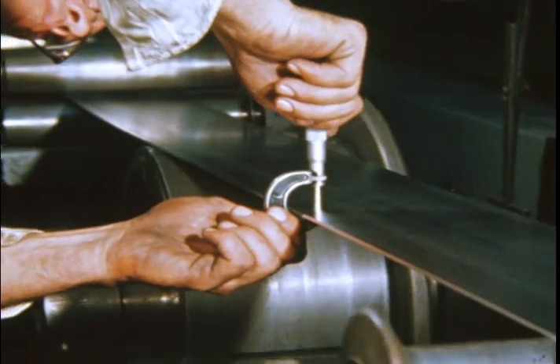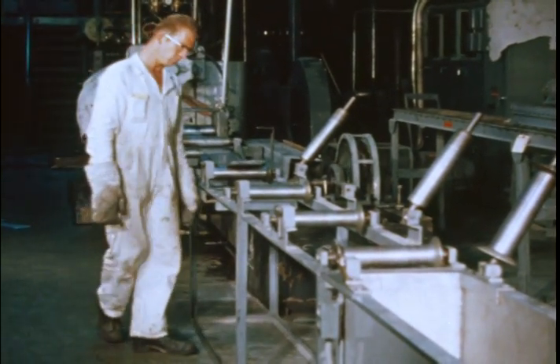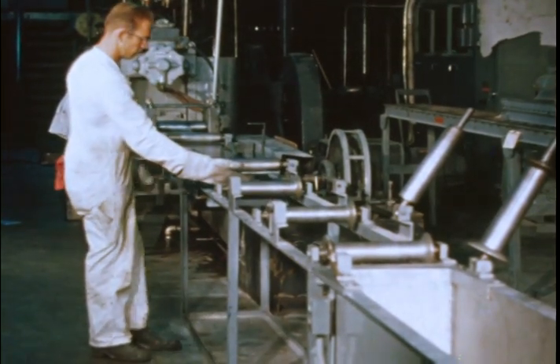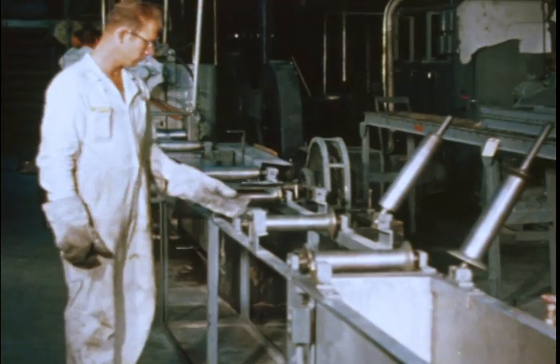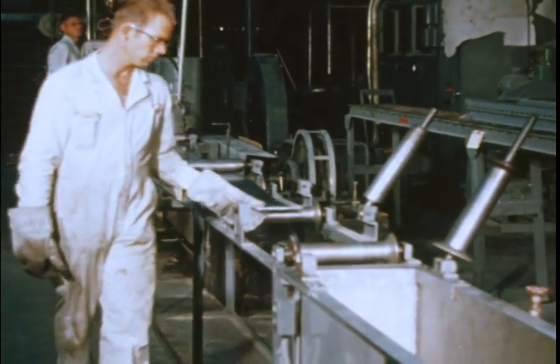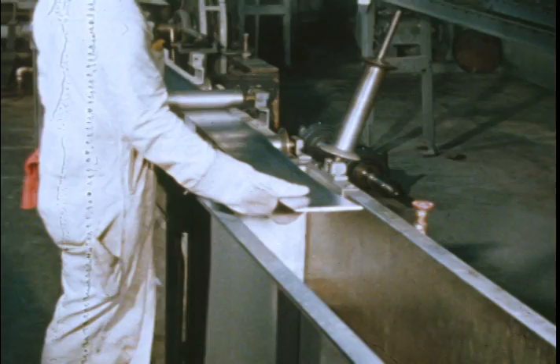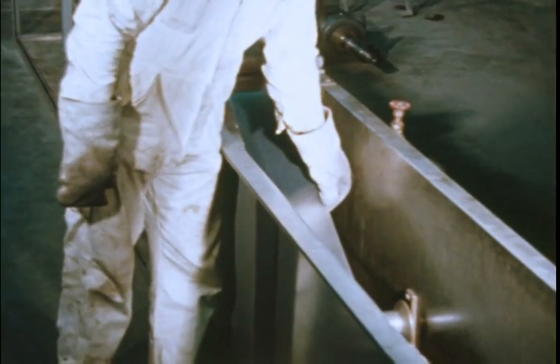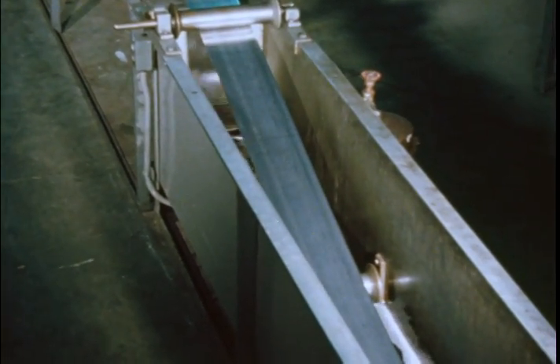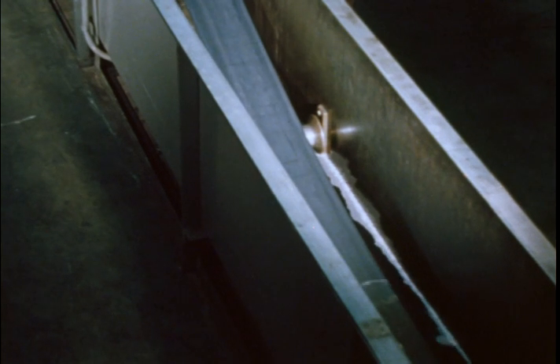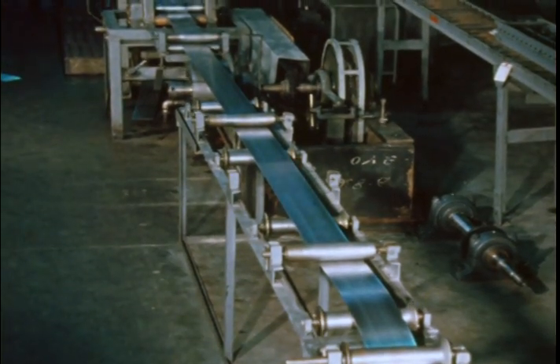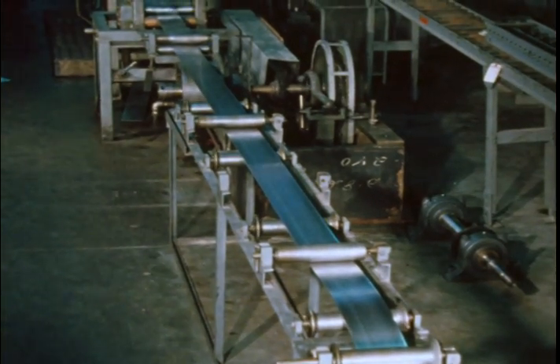The gauge is checked and the strip is carried over to the blanking press. Before blanking, it must be immersed in a thin lubricating oil. Pure aluminum, as we use here, is extremely sticky, and any tool or punch must be thoroughly lubricated to prevent sticking of the aluminum to the tool. This continuous casting operation is unique in the world today.